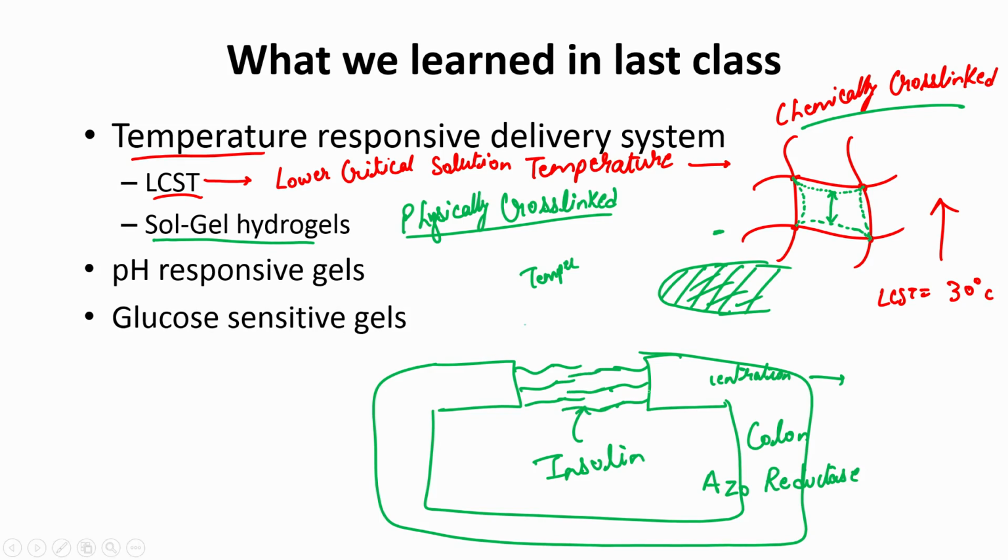these pores, but then a lot of an enzyme called GOD, glucose oxidase, was tagged to these polymers, and whenever enough glucose is present in the surrounding. So, let us say if a glucose comes, this is going to react with this glucose oxidase and produce H plus ions, causing a local drop in the pH. These things will change property with the local drop of pH and will shrink down and essentially become confined to the surface rather than spreading out, hence opening the pore for the insulin to come out.